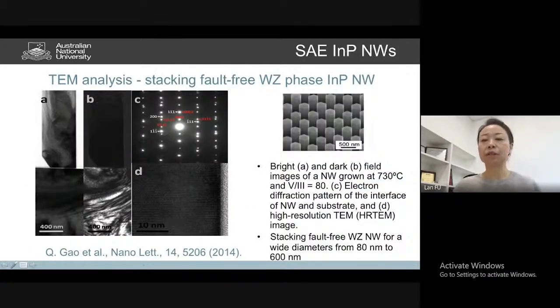After optimizing this, we're able to grow a really wide range of indium phosphide nanowire arrays with different diameters. Remember, we can open different holes onto the substrate, thereby we can control their diameter. And if we do structure analysis using transmission electron microscopy, we can really see the lattice alignment of our nanowire. We found beautiful hexagonal wurtzite-based indium phosphide nanowires without any stacking faults. This just demonstrates the high crystalline quality of the material.